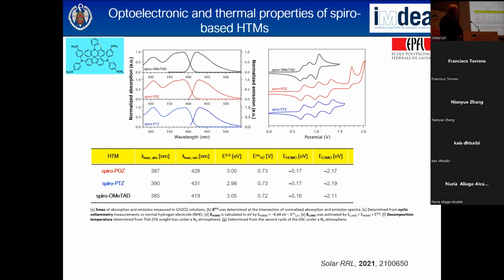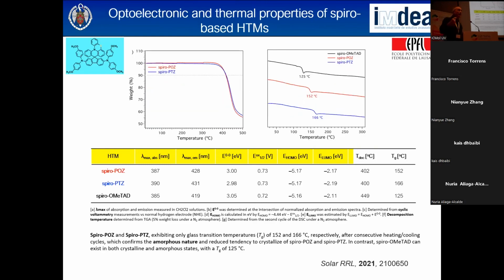Well, here are some optoelectronic properties. Sorry, these are the decomposition temperature and the glass transition for this system. The decomposition temperature is a little bit lower, but in our molecules, 400 degrees is much more than enough to be stable. But the glass transition is a little bit higher. That means that in our case, we could consider it mostly amorphous material, whereas the spiro is a little bit crystalline together with amorphous. Here are some differences. Sorry, I made a mistake here.